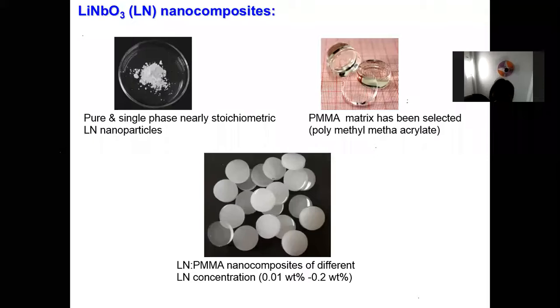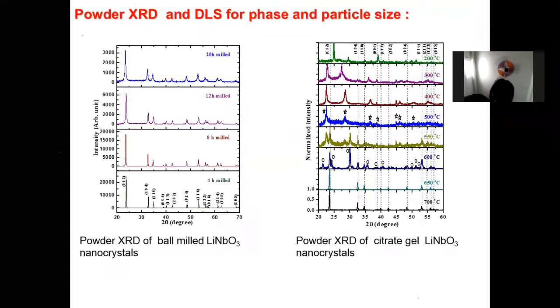But to make the single phase nanoparticles and then put them in a PMMA matrix and make this nanocomposite disc, it is very easy and very cheap as well. So you can use the disc for laser second harmonic generation rather than the single crystal, which is almost 20 times more expensive than these discs.